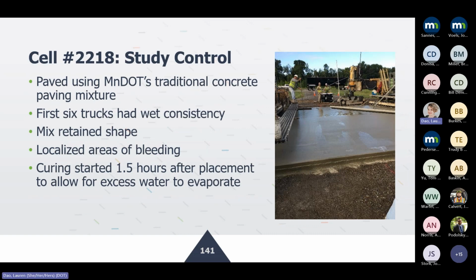And the control, you would not expect to see any issues with this particular mixture. They have been using it routinely. And one issue that was noted was in localized areas, we did see some excessive bleeding, and then we had to wait about 1.5 hours for all the bleed water to be sucked in or evaporate.